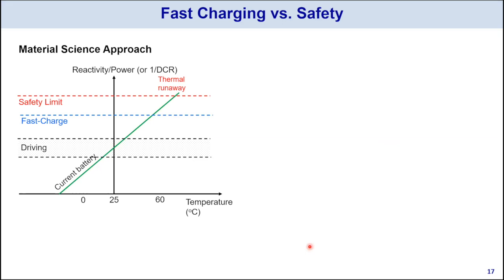Now, I just want to touch very briefly on the safety consequence of fast charging. In other words, the relationship between fast charging and safety, right? And this can be illustrated, again, by this sketch plotting the reactivity power level versus cell temperature. If you prefer a quantitative way, you can also use the inverse of DCR, DC resistance or internal resistance of the battery. Okay, and the state-of-the-art battery is shown as the green curve here. As we all know, those batteries are designed to provide enough power level for driving around room temperature, 25 degrees Celsius, and then as the temperature goes up, the reactivity and power level increase, and then there's a safe limit, beyond which you start to see the onset of thermal runaway. So we are not supposed to exceed this safety limit.